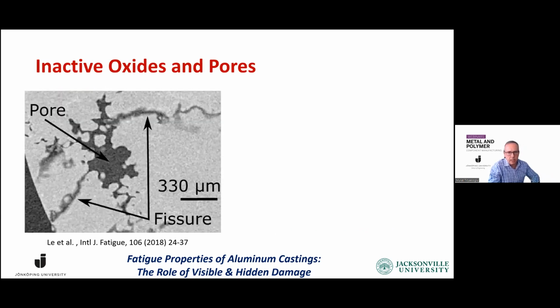And that's a little bit well known in certain circles. I came across this in the fatigue literature. There's the pore, and in fatigue, we would take this maybe as the initial fatigue crack initiating defect, but actually the extent of the damage is much larger. Here you see the interface, the debonded interface extending from the pore, and that's no wonder. In many studies, cracks were observed to start propagating from pores on the very first cycle.